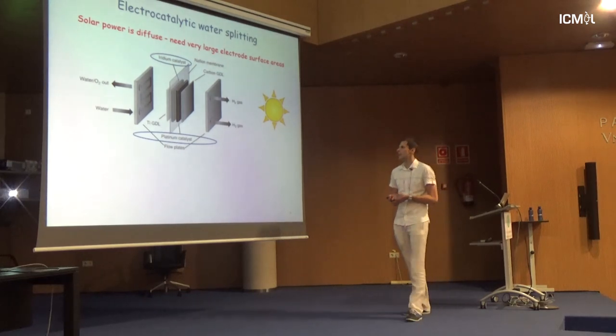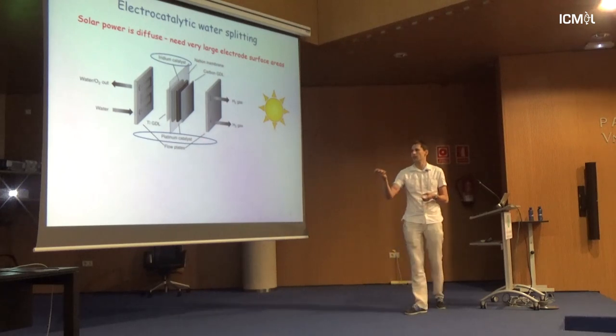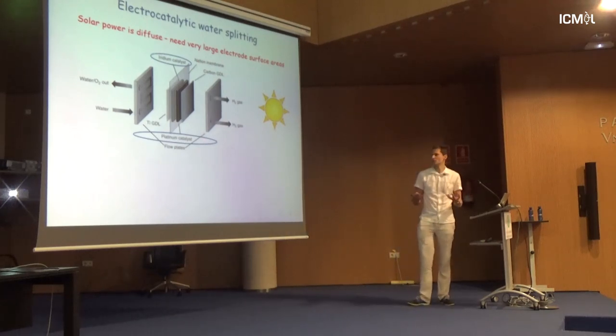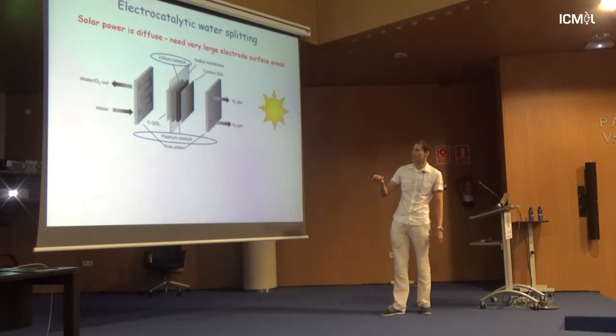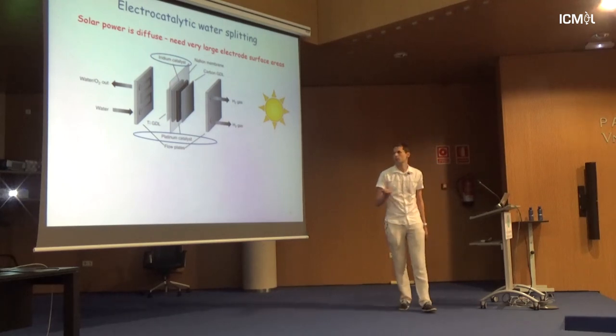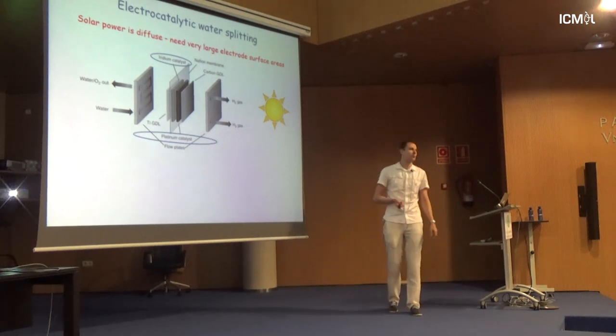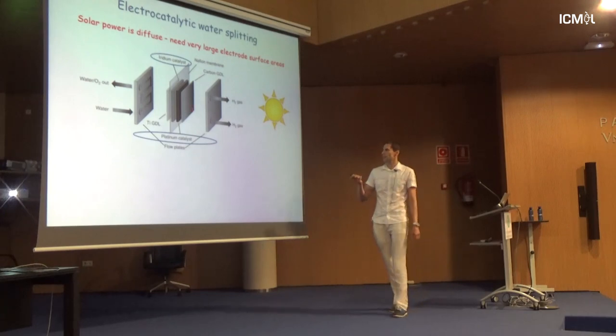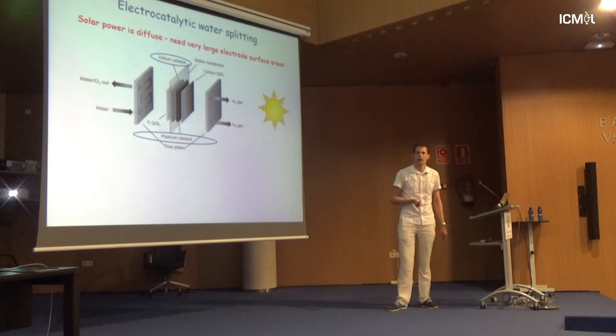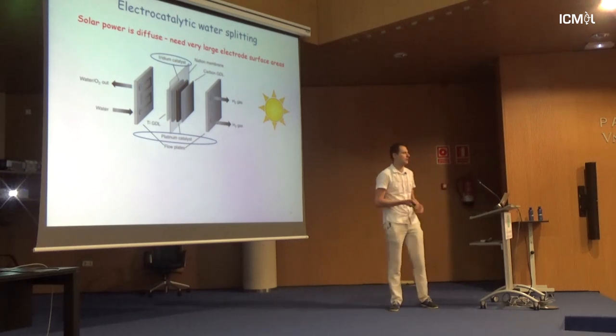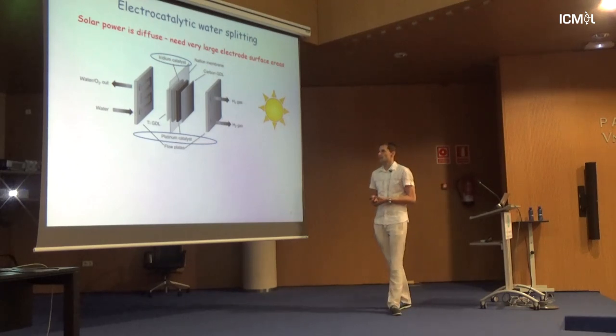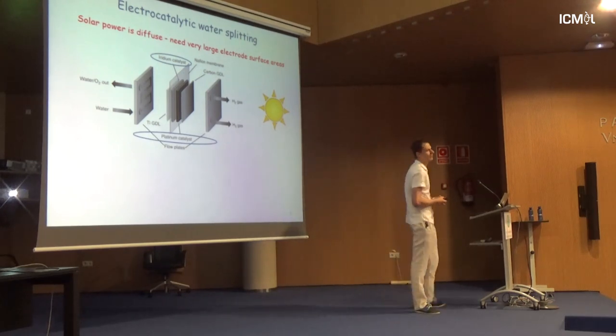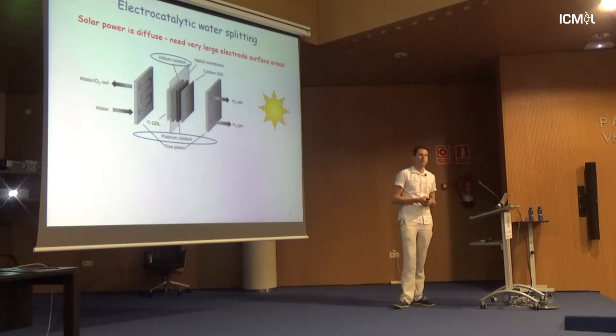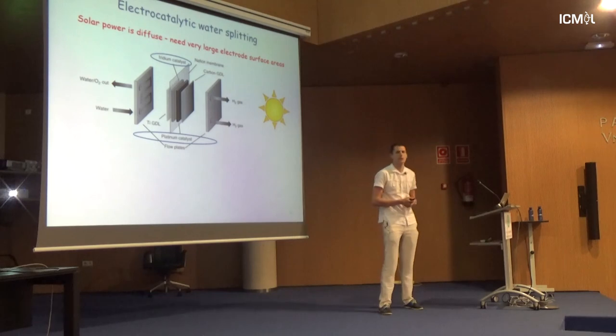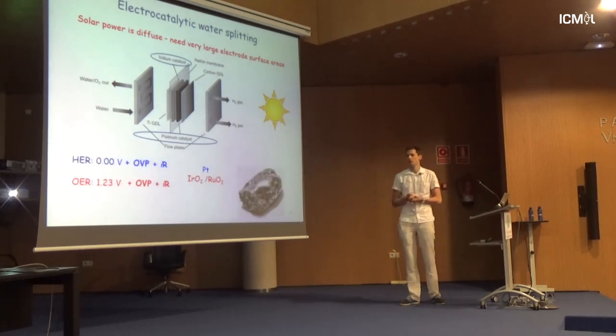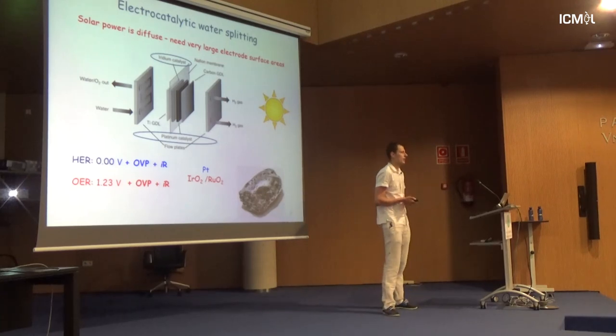This is another schematic of how a typical industrial electrolyzer looks like. So we have a plate, and we have a porous gas diffusion layer, normally titanium, and you have your iridium catalyst, or iridium oxide catalyst. Or you have your glassy carbon electrode, which is again porous, and you use your platinum catalyst. So in order to achieve reasonable current density and appreciable hydrogen evolution rates, you need a very, very high surface area. That means you need a very, very high consumption of your catalyst. Which brings an obvious issue. If we use platinum or iridium oxide, it's quite impractical.